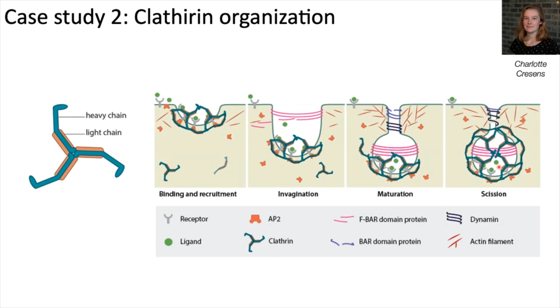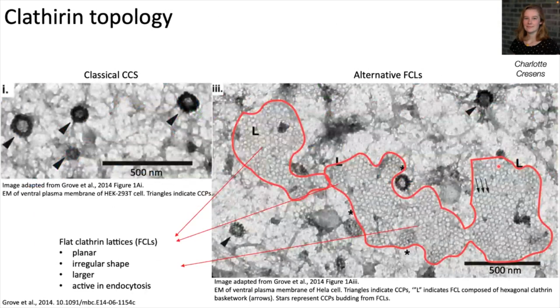But when you look at electron microscopy images of clathrin, you see indeed these vesicles that we call the classical clathrin-coated structures. They are around 100 nanometers, very spherical. But on the electron microscopy image, you also see these arrays of clathrin organization that do not form a vesicle. And literature describes this as flat clathrin lattices. And it's still a little bit unsure what their main purpose is. They also form vesicles. So you see here, for instance, a vesicle being formed from the edge of this plate. But further, what their real function is, nobody really knows.